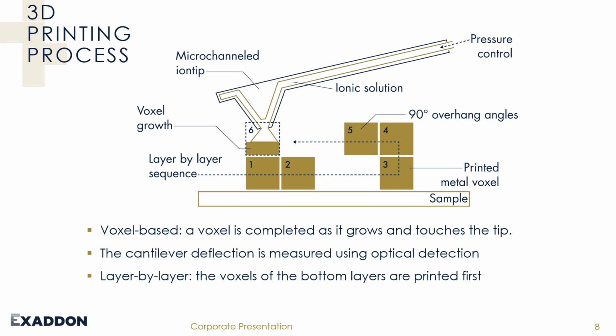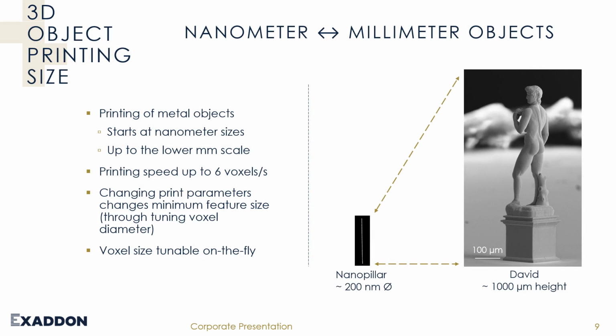So we are starting on level Z0, and then we build always in plus Z direction our structures upwards. And this allows us now to print objects as small as 200 nanometer pillars up to 1 millimeter objects, so 1000 micrometers. The nanopillars, we ended now at 200 nanometer. We are not following this path right now, but it might be even smaller, but 200 nanometer is what we achieved so far. And we can also print up to 6 voxels per second. And the voxel itself can vary in size, in diameter, and in height. So the volume we print over time can also vary.